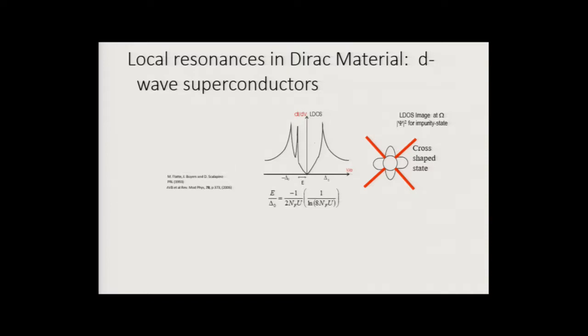So there's a Fermi surface. I have d-wave lobes, gaps, which go from plus to minus, and every time you go from plus to minus, you have to go through a node. I have a V-shaped density of states. And then every time I put a defect in, I have a resonance coming in and filling up the gap. So if I put in a defect, it's clear that actually if I have an unconventional superconductor at some